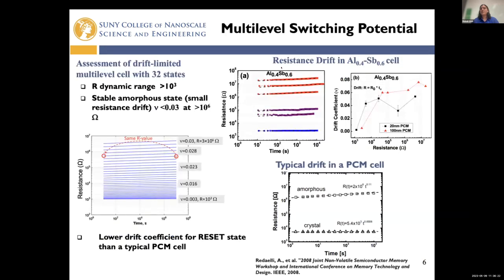Another property for multi-level switching is the resistance drift, which means that if you use the cell as a multi-level cell, the resistance tends to increase over time. If you have a high increase in the resistance, you have an overlap between different resistance states, and then the multi-level switching is not as efficient. Compared with the typical GST-based cell, aluminum 40% showed improved resistance drift compared to a typical PCM cell. So this was an overview of the talk that I gave at the IEEE SASC.